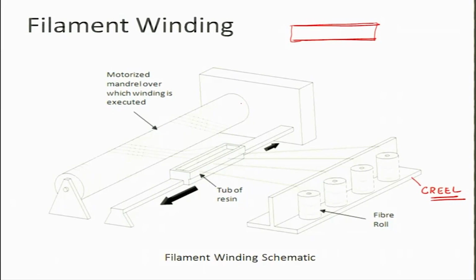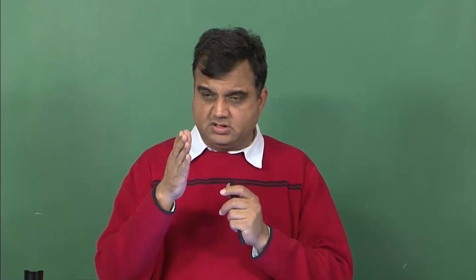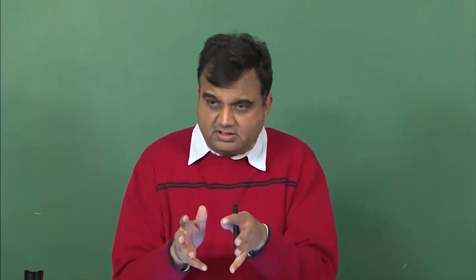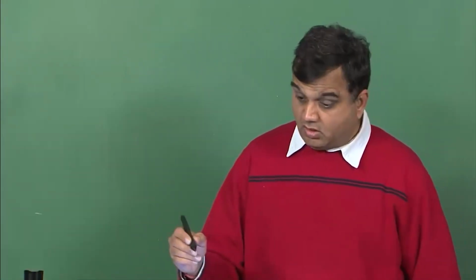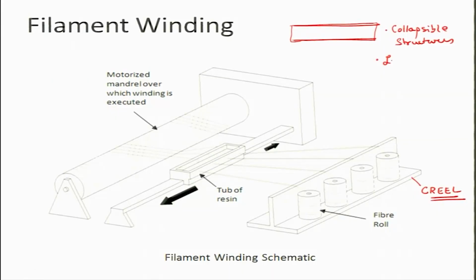So how do we make a mandrel? We can make it from collapsible structures. Once the thing is done, the inner mandrel collapses. It can be made of wood or metals, but which collapses at some specific locations, and then everything falls apart and only the outside thing is left. Or you can make it from low melting point alloys, in the sense that its melting point should be less than the decomposition temperature of the composite. Or you can make it from some salts, eutectic salts,